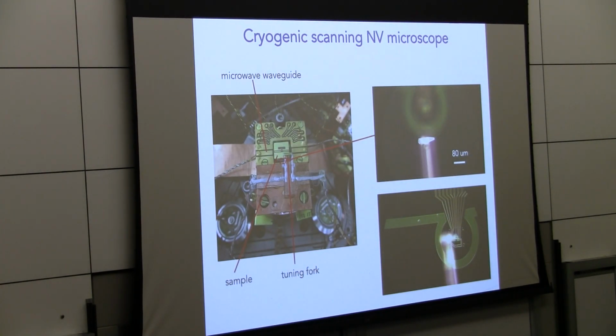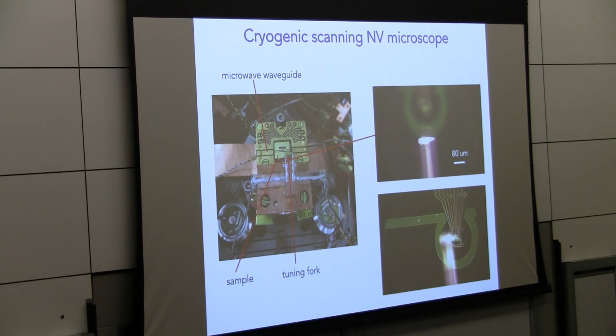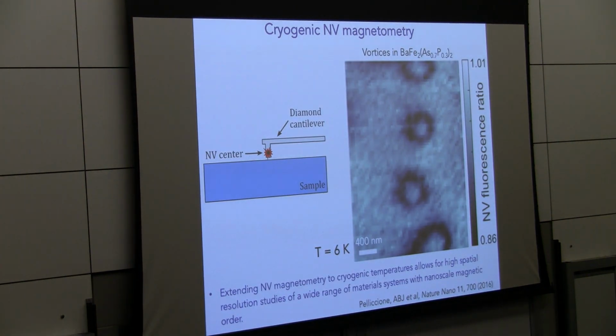And then we've integrated this scanning probe magnetometer into a cryogenic system, and this just shows a zoom in of our home-built tuning fork cantilever system with a diamond probe hanging off the end. You can see here the RF for driving the transitions of the spin. We have a microwave waveguide, and this just shows our diamond pillar, in this case I think over a graphene sample, where this is our microwave antenna, what we call an omega antenna. Okay, so this just shows you what our system looks like. A few years ago, our first successful demonstration of using the NV center as a probe of nanoscale magnetism in condensed matter systems at cryogenic temperatures was imaging vortices in an iron pnictide superconductor.